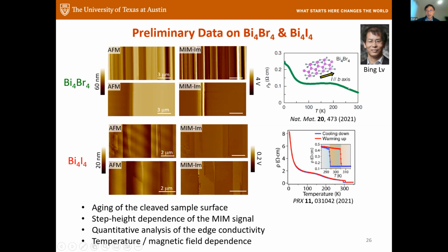criteria of the temperature dependence, they all go up, so the bulk, they're all insulators. But if you look at the numbers, these are done at 300 Kelvin, at room temperature. They are all on the order of 0.01 to 0.1 ohm centimeter. Different samples probably have different bulk doping.